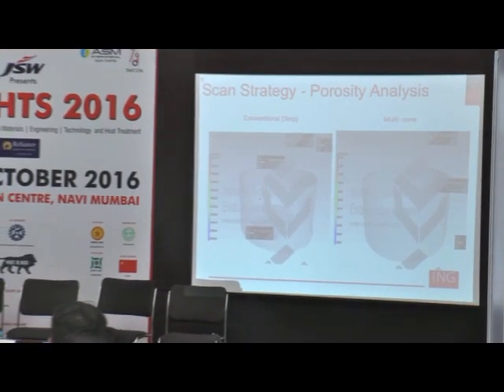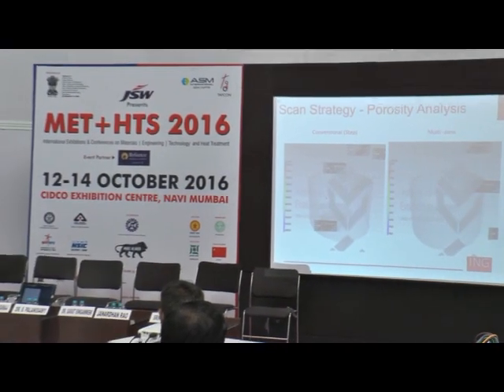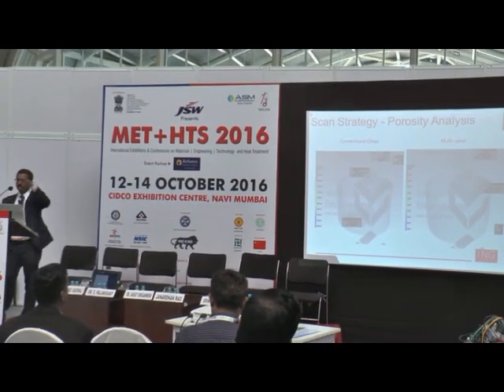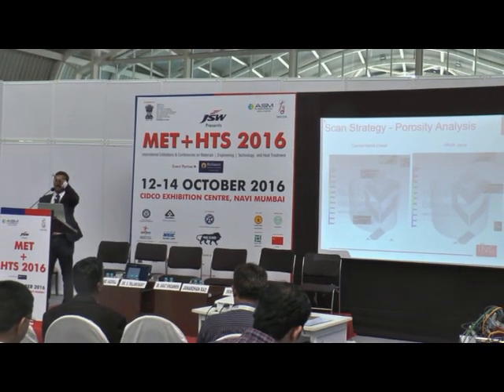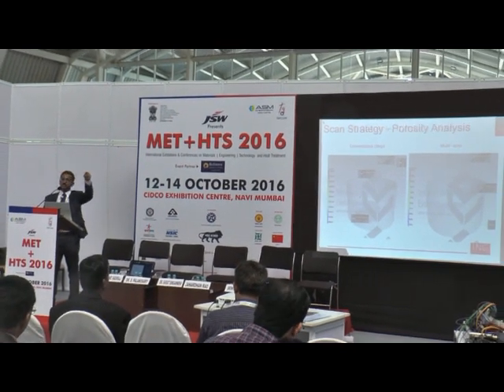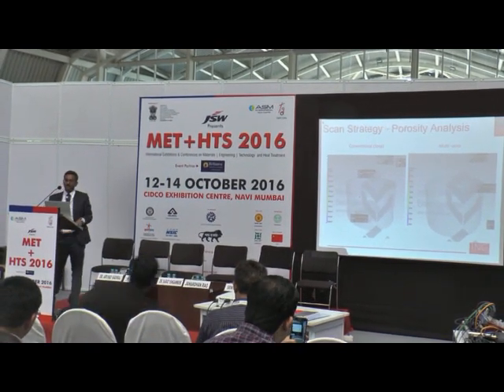And next one is the scan strategy. Unfortunately, I cannot show the strategy we have used here, but I can talk about it briefly. In this case, you're looking at a CT scan image. So a conventional step-by-step scan can be done, the raster scan: go in a line, step up, another line, step up, another line.